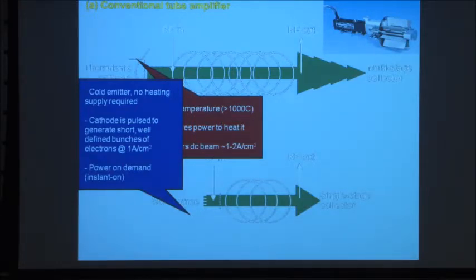However, if you try and use a CNT, then the CNTs you can modulate directly. You don't have to have DC. So you can get cold emitter, it's no heating, it's pulsed, it can generate short pulses, and power on demand. You don't have to heat them up like thermionic. But once again, you have to put them through a helix just to make them a bit more well-defined.